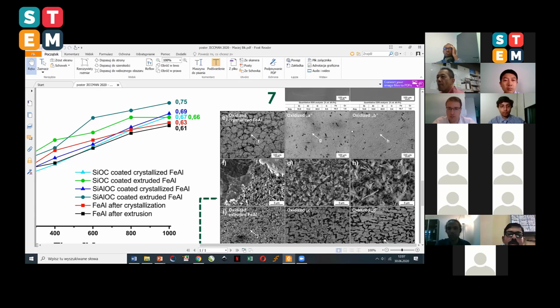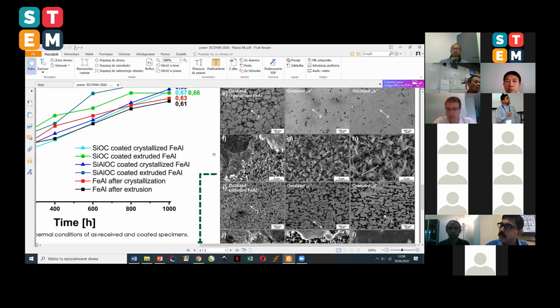So here on the E and F images, we see some images after oxidation of uncoated material and a full spallation phenomenon. And in comparison to that, after using our coatings, we see that the microstructure and morphology change considerably, and we see only some small cracks, small spallation sites. However, in comparison to uncoated material, the improvement is really significant. And then, using a higher resolution, we see that a multi-layered scale was formed.